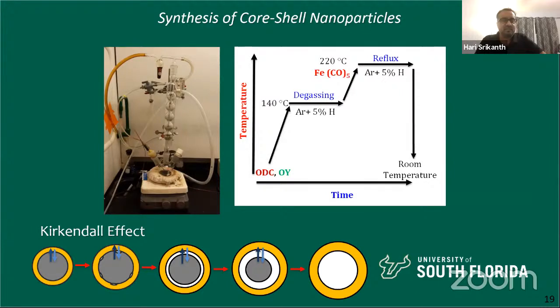Because iron is a metal, iron oxide is an oxide, of course, the differential diffusion of the oxygen ion and the metal ion is very different, okay? And because of this, there's an instability at the interface, and you have these little holes, voids opening up, and eventually over time, the hole gets bigger and bigger. Guess what? You end up having a hollow nanoparticle. Basically, the shell increases because the iron oxidizes and becomes iron oxide. And essentially, you start off with a core shell, and over time, you end up with a hollow shell. So if your goal is to make hollow nanoparticles, this is the way to go.